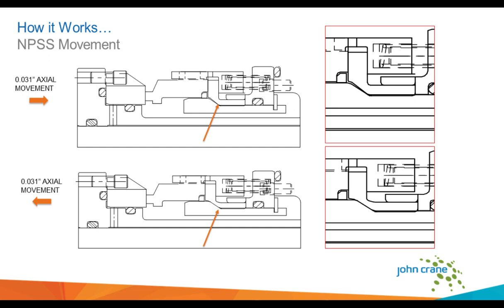And then that high-strength anti-extrusion ring, which is in the lower left of the blown-up screen, will help keep that elastomer from extruding. But when it moves to the left, it moves along with the primary ring, tracking that, and putting that load on the face, keeping it a constant load on the face, but also providing the seal that's required during the shuttling. This concept was tested over 8 million shuttles, or 8 million cycles, and there was no damage to that elastomer ring.